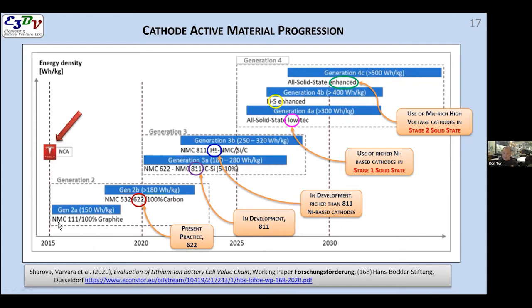You can see that nickel manganese cobalt oxides that were 111, that was kind of the Gen 2A, because lithium cobalt oxide was the easiest one to make. It was very easy to make. You can take cobalt powder and oxidize it and lithiate it very easily in a two-step process. NMC 111 is almost as easy because it's an equimolar amount of each of these, and bang, there you go. Very easy to make material. So that's kind of the starting point here.